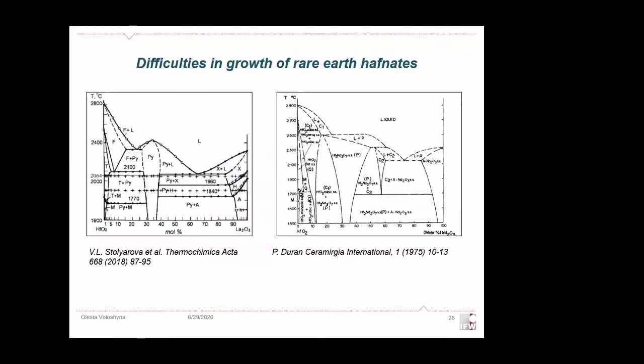But the main difficulties with obtaining these rare earth hafnates is that, first of all, they have very high, extremely high melting points, about 2500 degrees. And the second problem is that for some of the rare earth hafnates, the pyrochlore structure is decomposing, so we can't obtain it from the melt, or we need to use some special technique for growth.